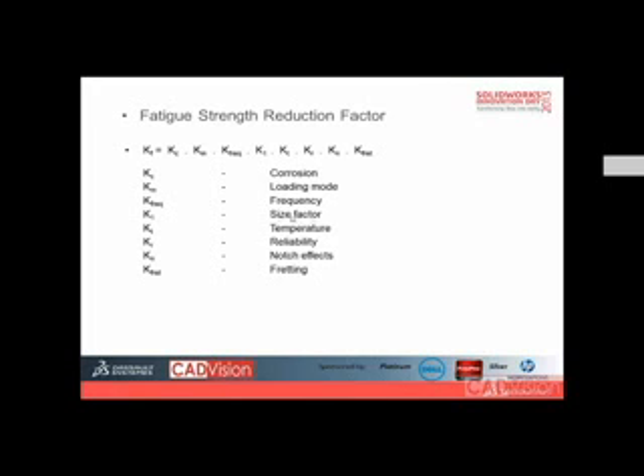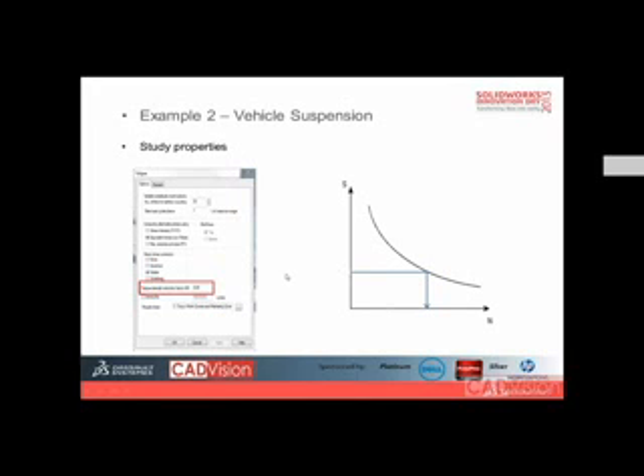If let's say we have bad control on the tolerance, then the size factor could be low. If we have a not careful manufacturing process, for example, we can make some scratches. If there is some damage under transport, and so on, then we have to adjust the effect correspondingly. So this is finally how we accumulate the fatigue strength reduction factor. In this case we choose 0.61 using a reference.